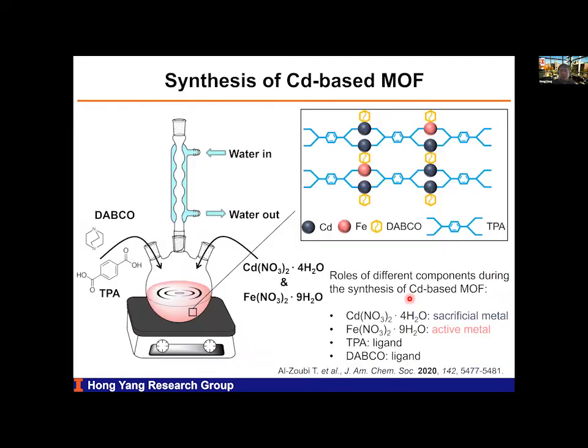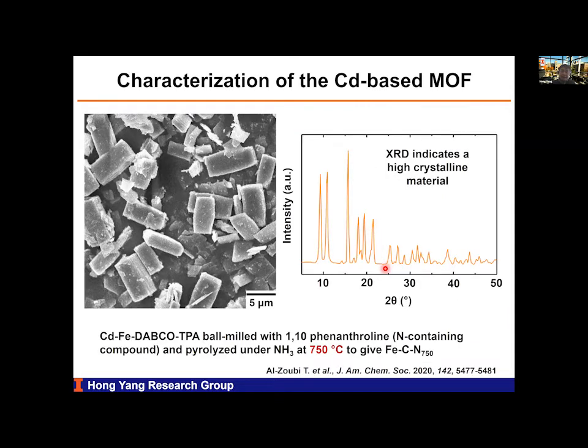To do so, we identified several different types of precursors. This is one of the combinations. The key development besides the metal part is the choice of a new type of MOF precursor, the TPA and the DABCO ligands. These are the molecular structures that can be seen here. By using these bidentate ligands, we were able to form the MOF precursor with good crystallinity. And this allowed us to start to think about the fine dispersion of atomically separated structures, uniformly distributed along the molecular matrix. To do so, we also use ammonia, and the pyrolysis was developed at 750 rather than the commonly used 950 for this study.